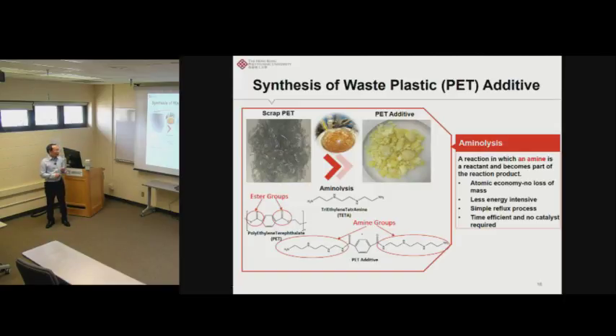And also another change is originally the waste PET has a very long chain structure. You notice the number N here. That means it has a relatively long chain. And after the reaction, actually we cut the long chain into short pieces. So basically we degrade the material. So two things happen. First is that we degrade. Second is we introduce the amine groups into the material.